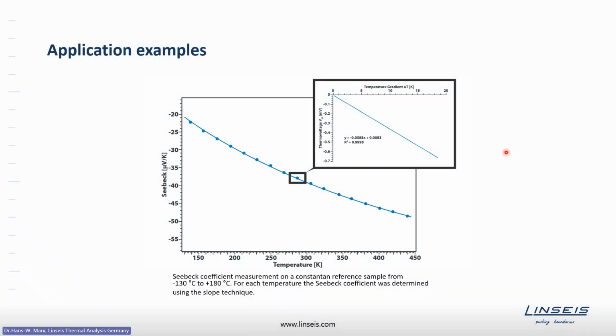The last example I want to show is a measurement of the Seebeck effect using the Seebeck option on the HCS. In this case, a Constantan sample was analyzed. Constantan is also used to check the performance of the instrument. This Constantan sample was investigated in a range of minus 130 to plus 180 degrees centigrade. And you find the Seebeck coefficient depending on temperature.